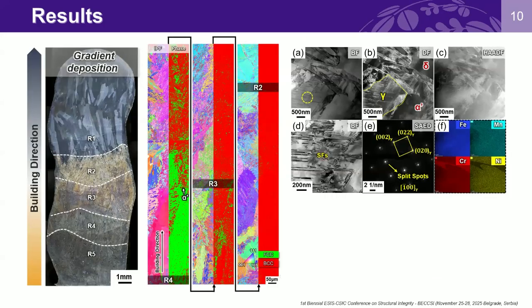In the gradient deposition sample, a more complex variation in phase fraction can be observed, particularly between the martensite and the retained gamma austenite. It has been widely reported that the ductility of martensitic stainless steels can be improved while activating the TRIP effect, which relies on introducing retained gamma austenite. Given such a unique microstructural distribution, its mechanical property and deformation behavior are highly worthy of investigation.